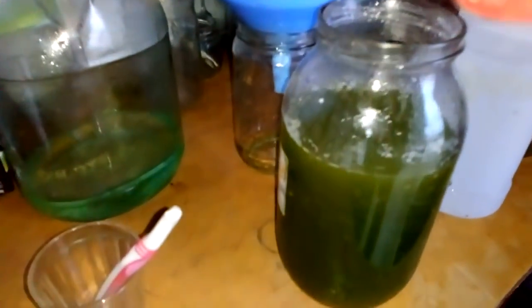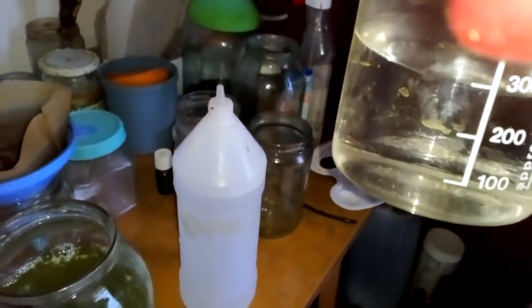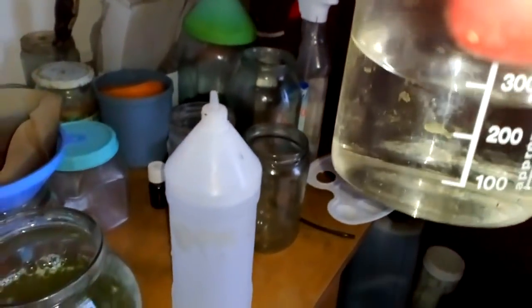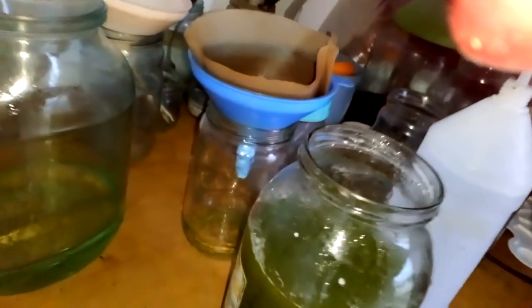Here in that jar I got the whole solution. It's a lot of solution because there was a lot of material, a lot of fiber, and a lot of that silicon die. And here in that beaker I got three spoons of SMB dissolved in distilled water and heated to 60 degrees. So let's now drop the gold.